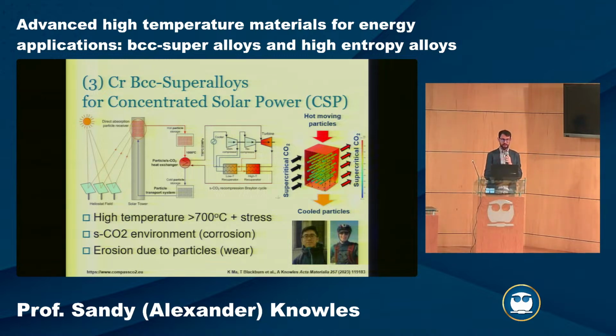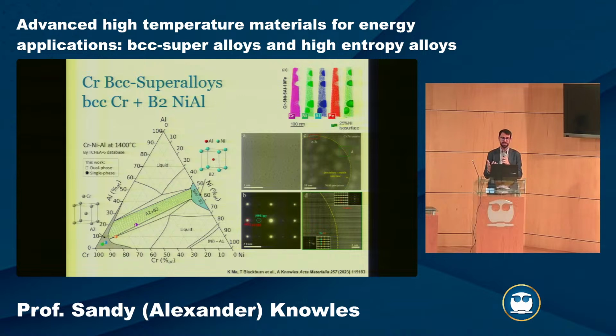Within this specific system, we were looking at using a supercritical CO2 power cycle. Rather than steam turbines, if you go to supercritical CO2, you get advantages in terms of the density of the product, but also the thermodynamic efficiency. But if you go to this system with high temperatures of 700 degrees, you have supercritical CO2, which is also corrosive, and then you have erosion from the particles. This is a pretty wicked problem in this kind of heat exchanger geometry, where you have tubes with particles flowing over them and supercritical CO2 flowing through them. It's a pretty demanding condition, and so we wanted to look at what new materials might be able to withstand those conditions.